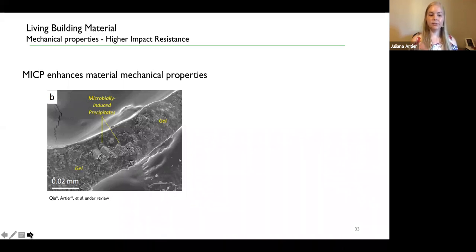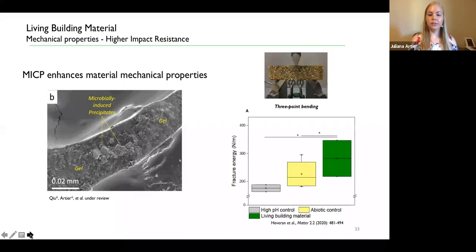And as you saw, we had an improvement on compression, but we also have an improvement when we look at this 3-point bending experiment. They're done by the engineers, where you put pressure in the middle and you see if these bricks will break. This is important to measure impact resistance of the material. And if we compare the samples with simply the chemical precipitation of calcium carbonates by raising the pH or just in the media, we can definitely show that the bacteria in MICP have an increased effect on the fracture energy, as we showed before.